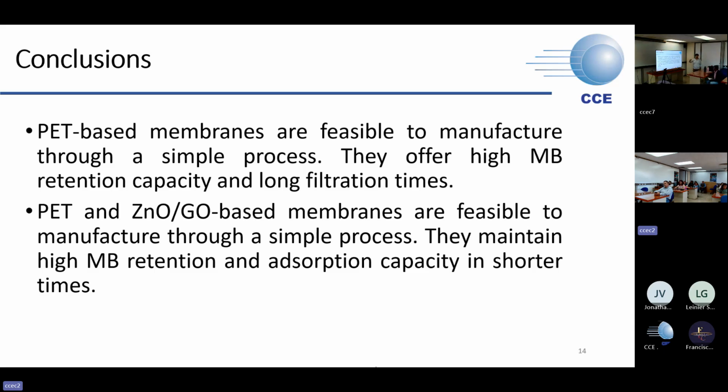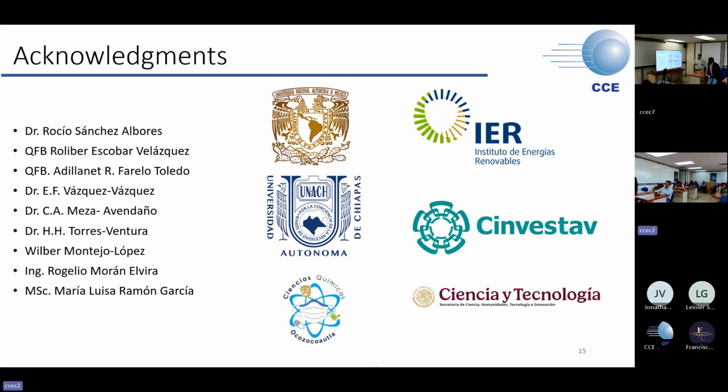With this result, we are now incorporating new materials, for example, biochar or activated biochar. With these materials, we have observed better results than when we use only PET. Another interesting thing that we have observed is that when we store our used membranes with the dye in a Petri box and leave them in the laboratory, with time these membranes can clean themselves because of the presence of these particles. But this is something that we have not reported.